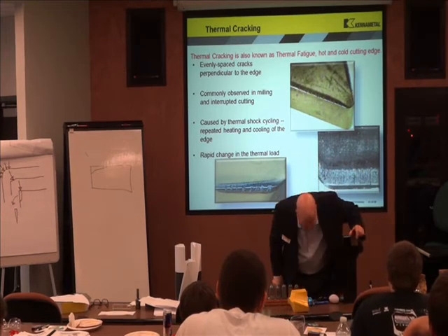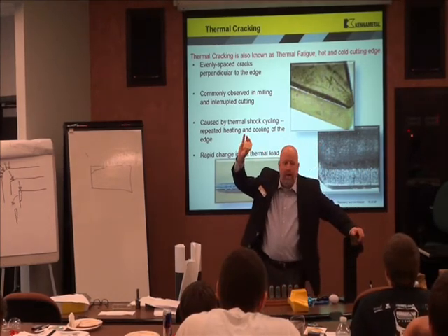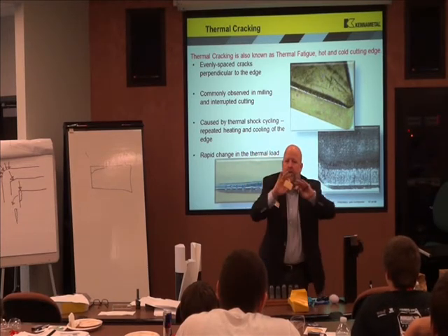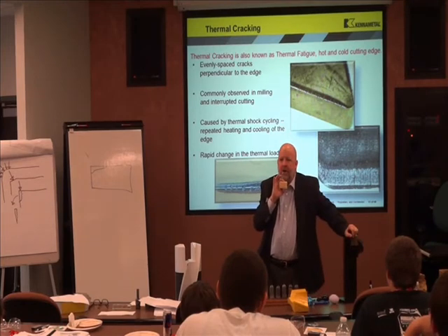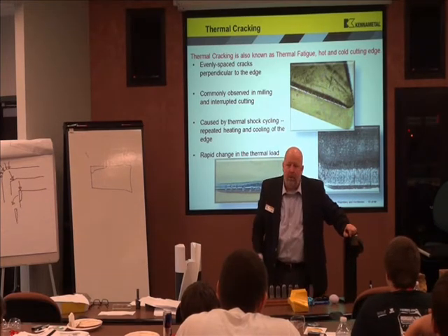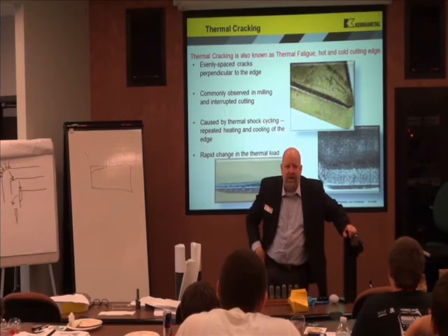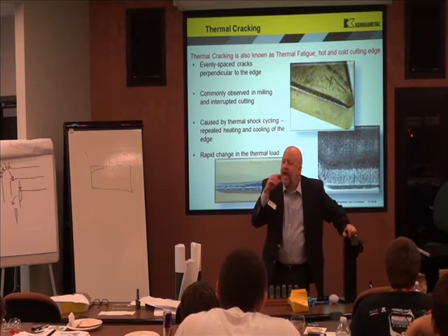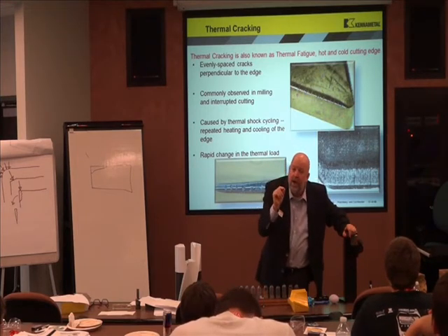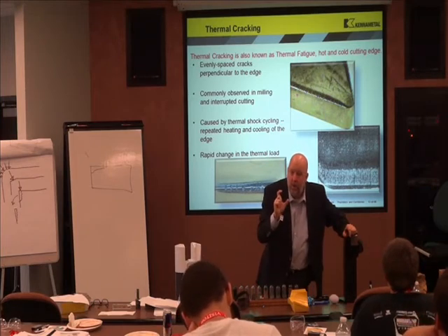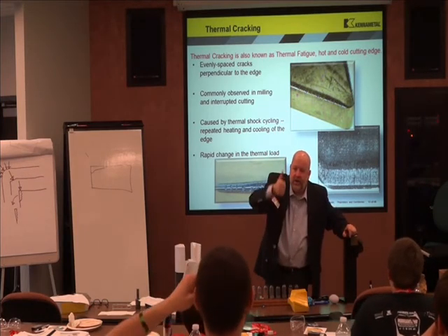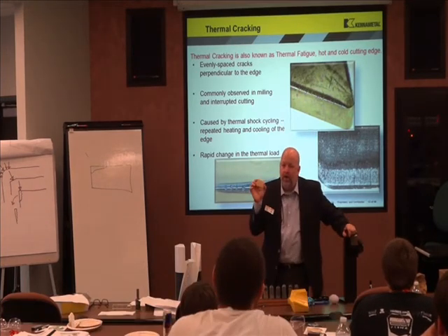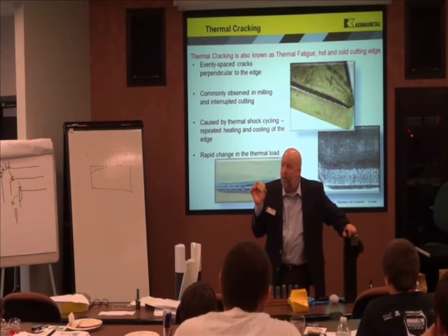Now, oops, here we go. Of the three basic elements in carbide, which one do you think I put more in to absorb that expansion, contraction? Cobalt, marshmallow. If I put more marshmallow in, do I go faster or slower? This is counterintuitive. Everybody thinks if you're running a graded carbide that can run wet, you're going faster. But that's wrong. Carbide that you run wet must have more cobalt. Cobalt melts. Marshmallow melts under heat.